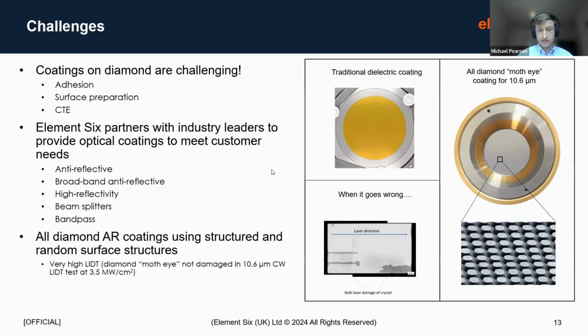Yeah, and the final thing, just to say that the image in the middle there is a good example of when coatings go wrong. So this is a Raman crystal that has been coated on its end faces with an anti-reflective coating. The direction of the laser in this image is from the left-hand side to the right-hand side, and you can